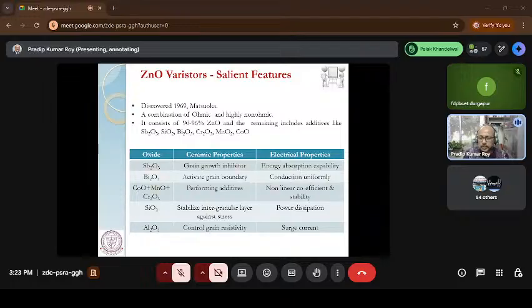The major oxide is zinc oxide, and apart from zinc oxide, there are other 6-7 oxides used, like antimony oxide, silicon oxide, bismuth oxide, chromium oxide, manganese oxide, and cobalt oxide. What exactly their functions are is still unknown, but people have made some assumptions about what they are doing. There are two kinds of prospects: the material prospect, why this material is used, and the electrical prospect, what this material is doing in the electrical parameters.